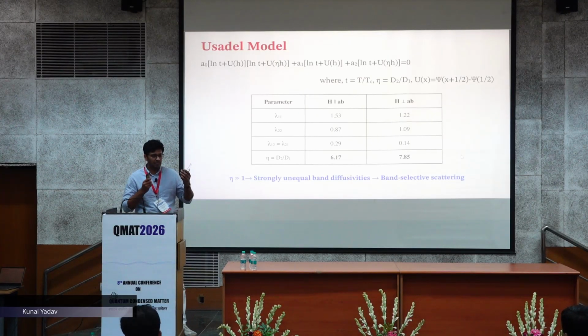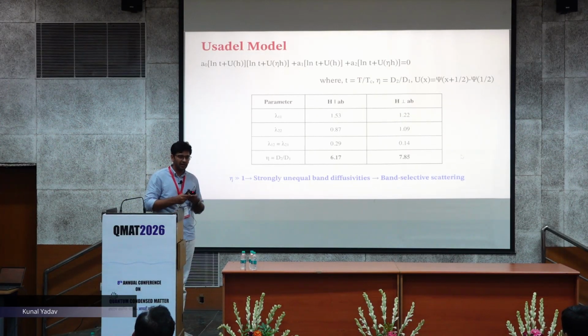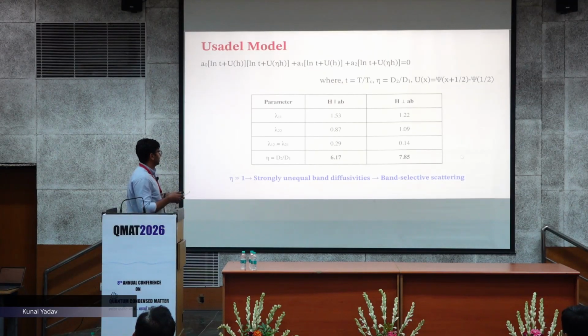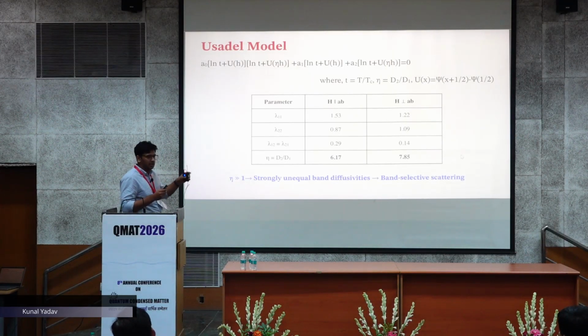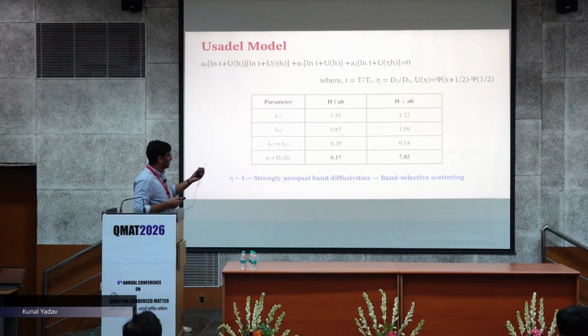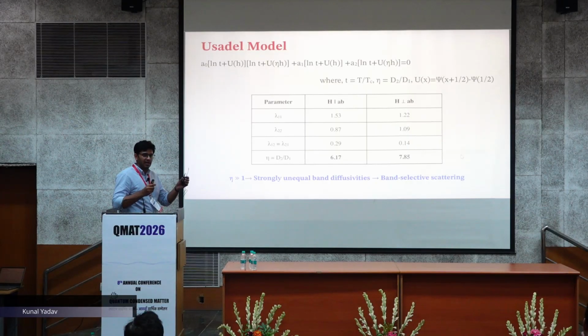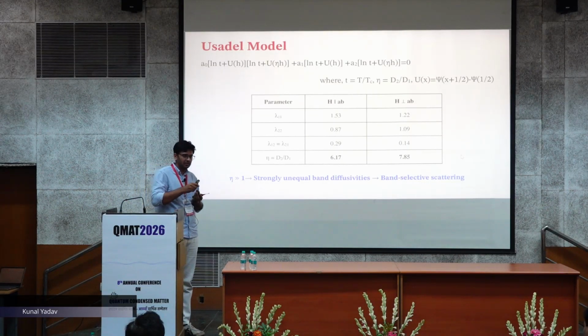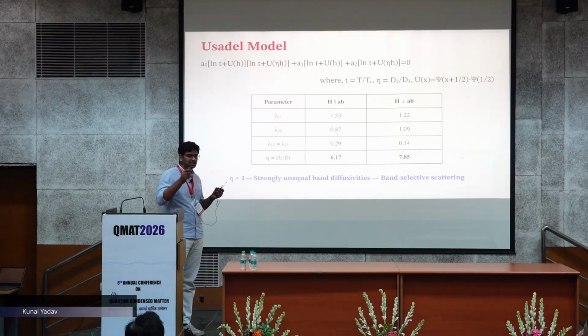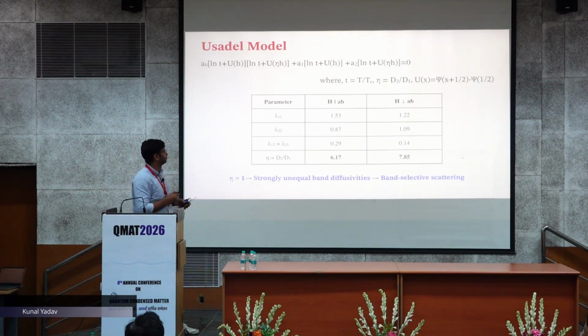Either they can contribute, they can interact in intraband or interband. So the interband connectivity here, lambda 1-2 or lambda 2-1, is less than the intraband connectivity interaction. This means this is a two band model, but the interband strength is lower. This means that the intraband connected with the interband contribution, which means it has a single TC there.